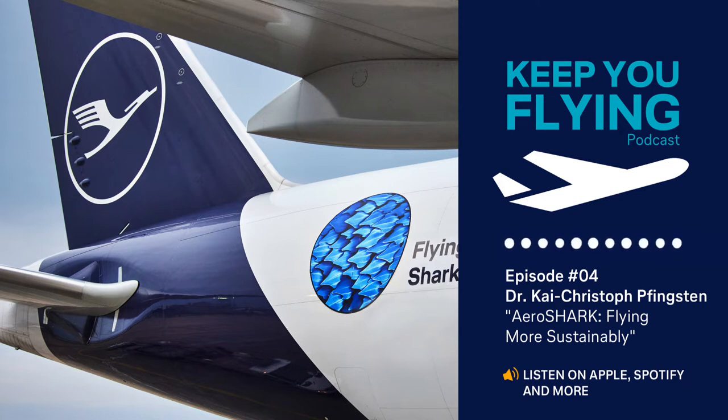The first challenge is the material. The surface structure, consisting of riblets measuring around 50 micrometers, imitates the properties of sharkskin and therefore optimizes the aerodynamics on flow-related parts of the aircraft. Microstructures are very small, and a commercial aircraft is very big. In addition, the durability of the material is very important. If you are able to get the microstructures on the surface, you want them to endure in this demanding environment as long as possible. The impact of high-velocity particles could just remove the riblets. Strong UV radiation could destroy the material or change its properties.